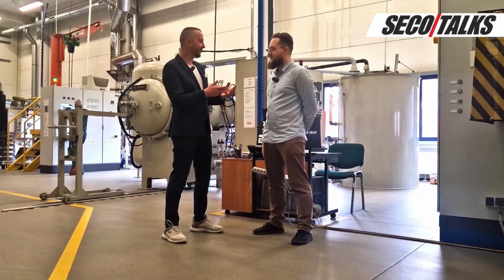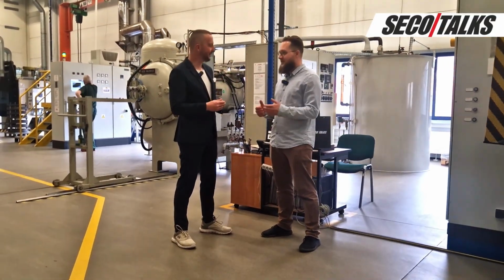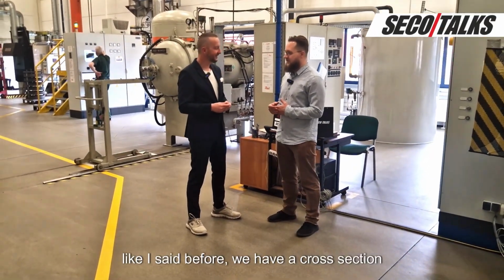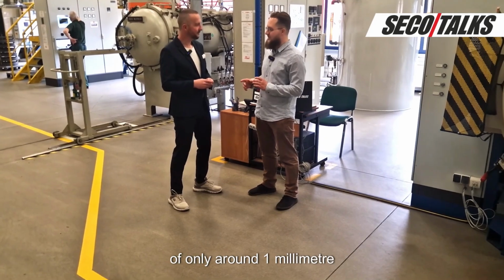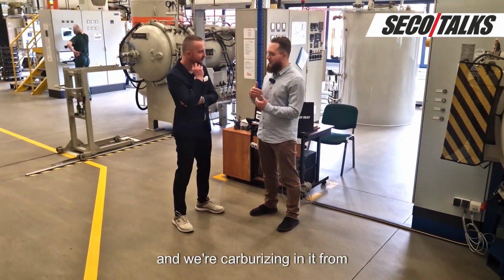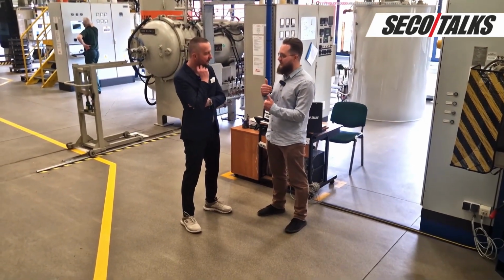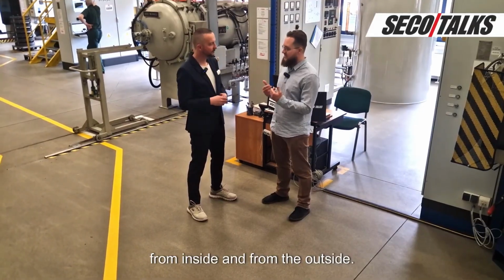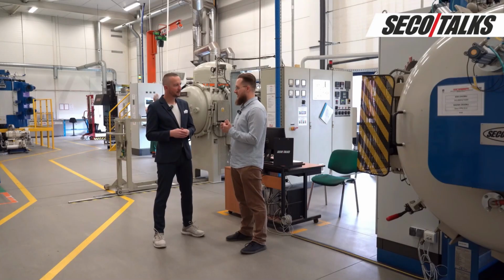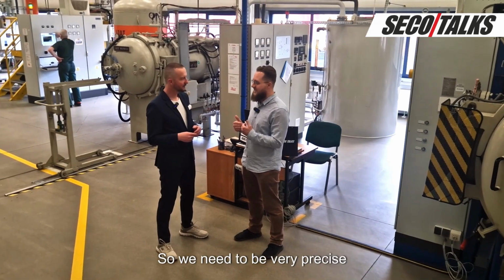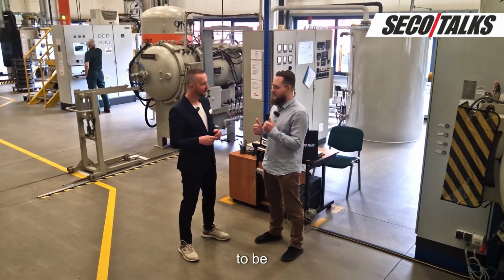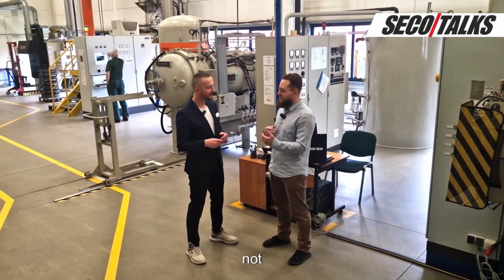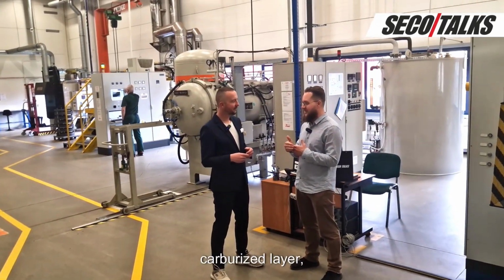Where is the precision? What do you mean? Okay, like I said before, we have a cross-section of only around 1 millimeter, and we're carburizing it from both surfaces, yes, from inside and from the outside. And we still want to maintain an uncarburized core in this section. So we need to be very precise to not create too thick a carburized layer.